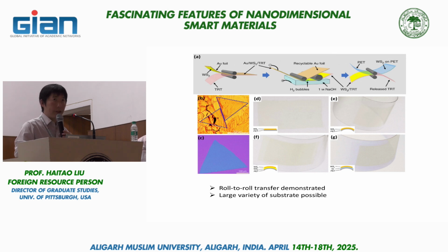And on the left is this triangle shape, that's an atomic force microscope image showing a large domain of the TMD grown by the MOCVD process. Again, the shape is related to the underlying crystal lattice. A lot of the TMDs have threefold symmetry, so when they nucleate and grow, they grow according to their crystal symmetry, and oftentimes that gives you a threefold or sixfold shape.